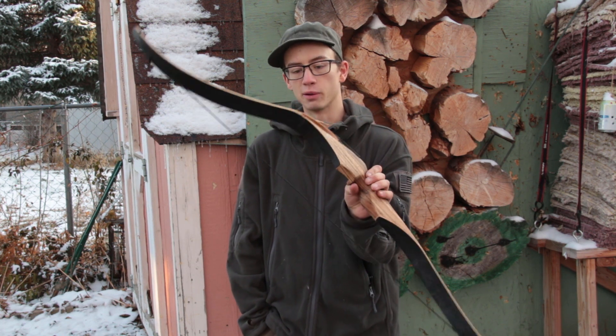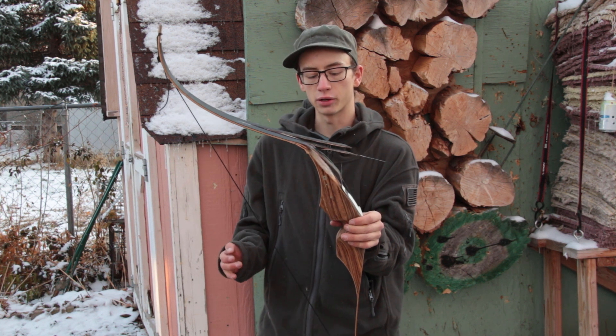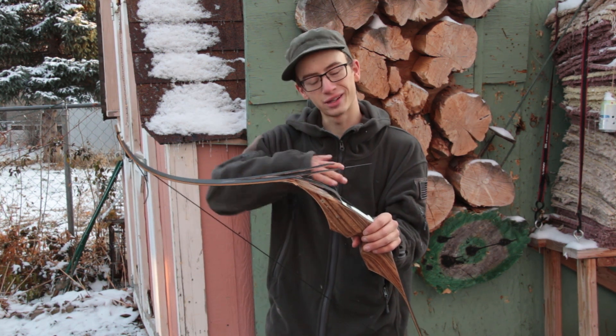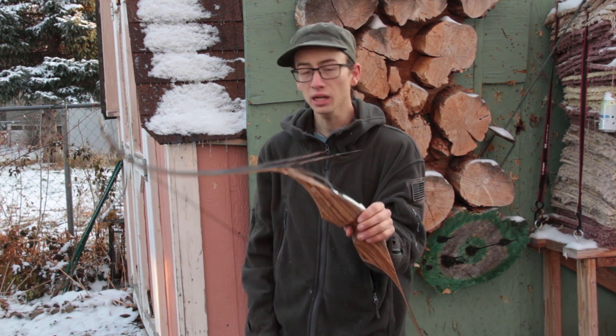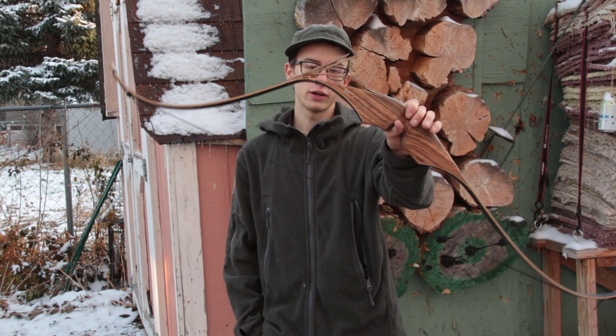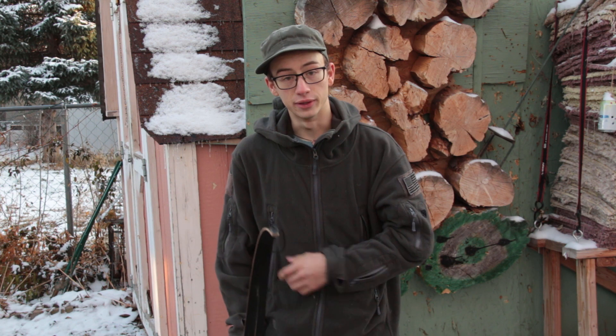We got to see what might happen if your bow delaminates. This one was fairly tame — I have seen a lot worse happen at archery ranges, and I think that's just because it was already pretty well cracked, so it kind of just peeled apart. It's also pretty cold out here, which does make the glue a little bit more brittle. But very interesting to see. I hope you enjoyed this video and I'll see you next time.